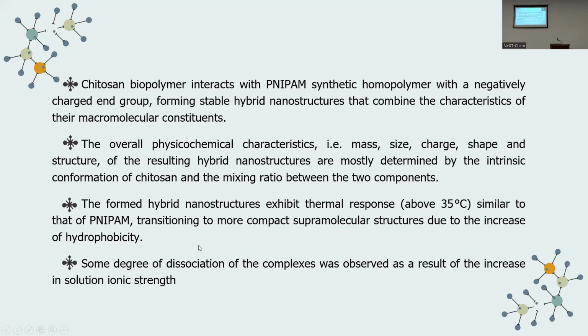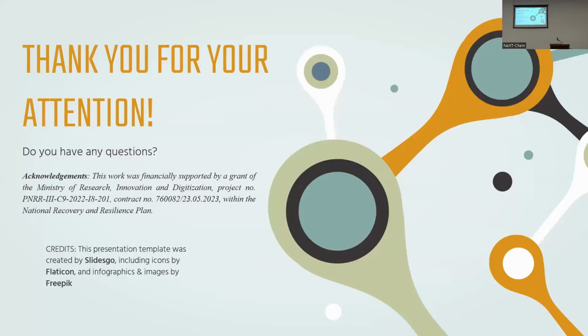The hybrid nanostructures exhibit thermal response above 35 degrees, similar to that of PNIPAM, transitioning to more compact supramolecular structures due to the increase of hydrophobicity. And also, we see some degree of dissociation of the complexes as a result of the increase in solution ionic strength. Thank you for your attention.